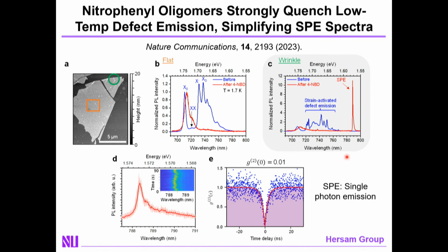More interestingly, though, is when you go to low temperature. So when you go to low temperature and you look at tungsten diselenide, the photoluminescence spectrum becomes somewhat more complicated. There's a number of excitonic and trionic features in addition to defect states that we talked about before. And when you add the organo-functionalization layer, what you observe is quenching of those defect peaks.